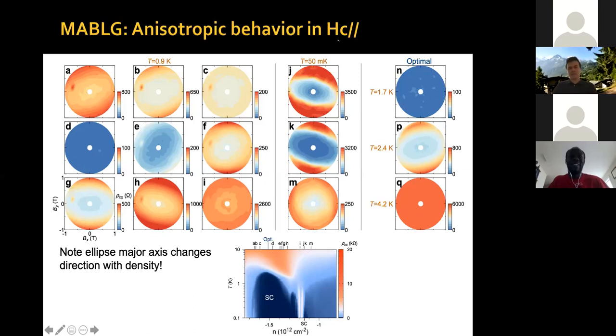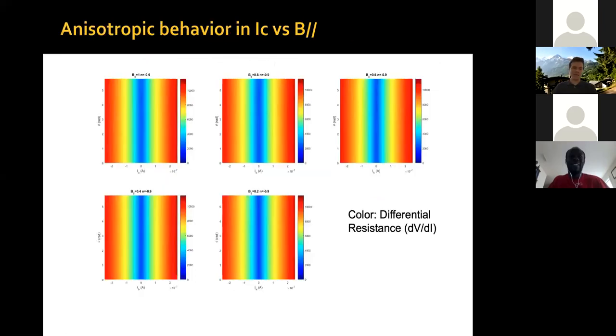Okay. So I was saying that we can measure these ellipses in the critical field. But for that, sometimes you have to bring the system to relatively high temperature. You have to bring it out of the superconducting state by applying a large magnetic field. We can do an alternative measurement, which is we can keep the system at low magnetic fields and at low temperature, always at base temperature, but now run a large current. So we can measure if the critical current also has any anisotropies. And indeed, it does.